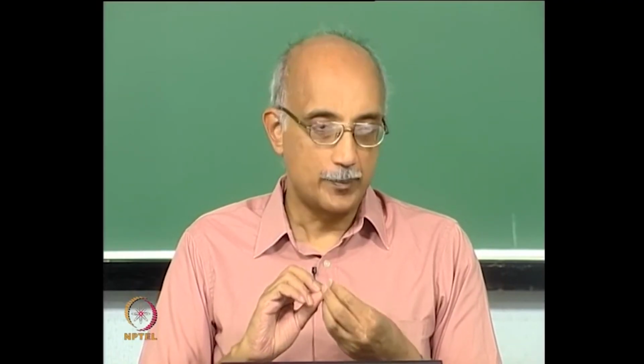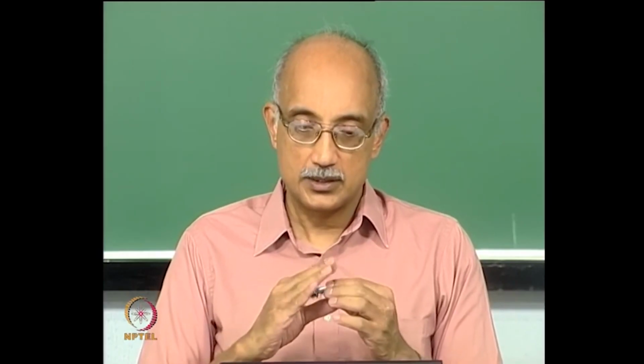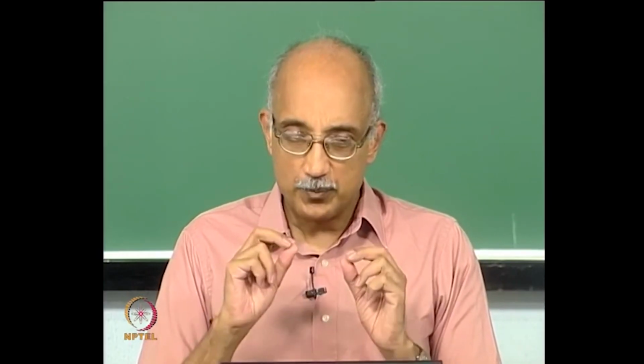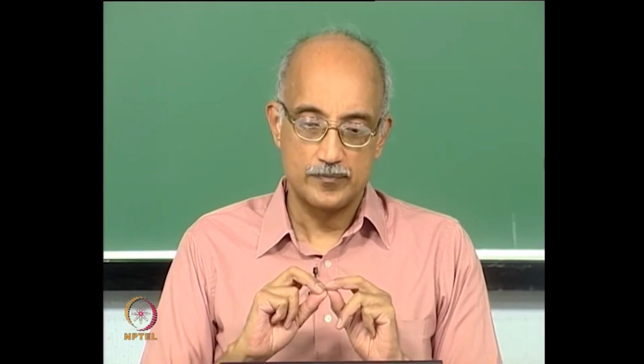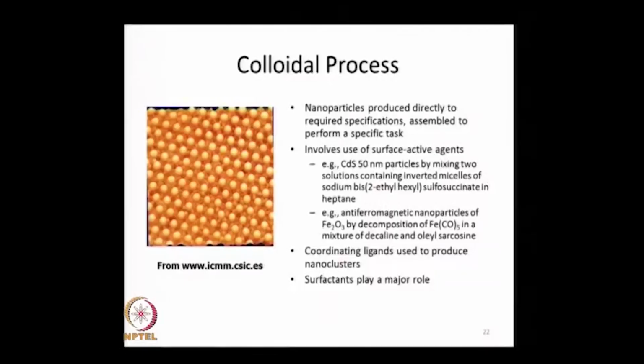So, it is a more complex process compared to, for example, the top down approach, but the advantage is that you have very precise control over the physical structure as well as the chemical properties of the resulting nanomaterial. Some of the examples are 50 nanometer particles of cadmium sulfide that is produced by mixing two solutions containing micelles of sodium sulfosuccinate in heptane.